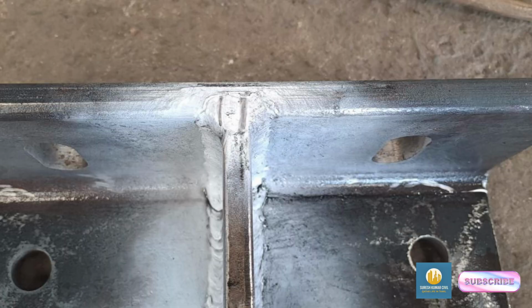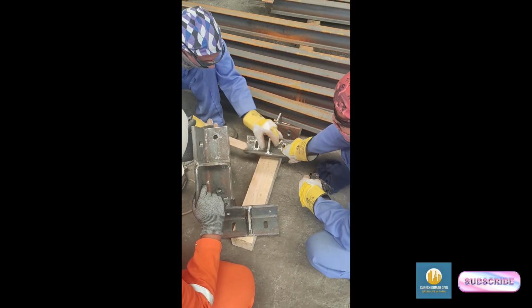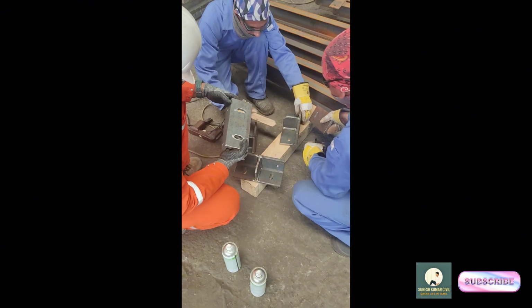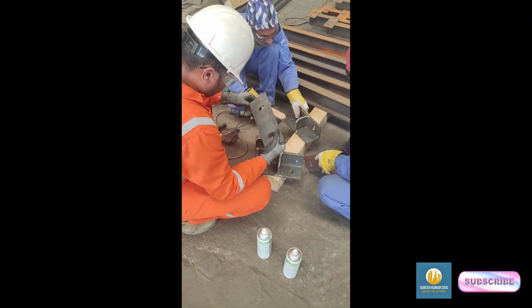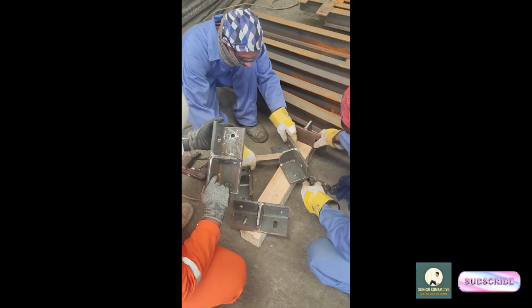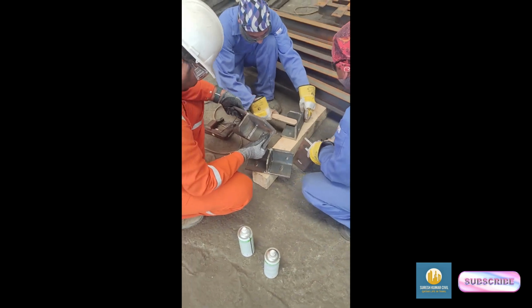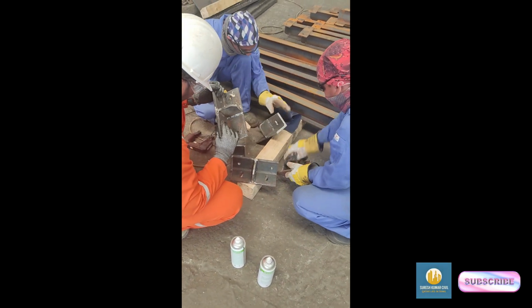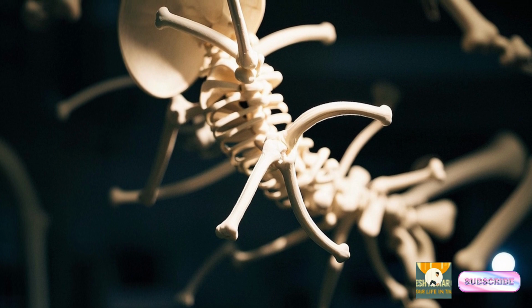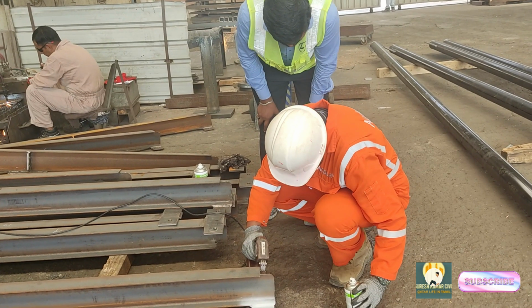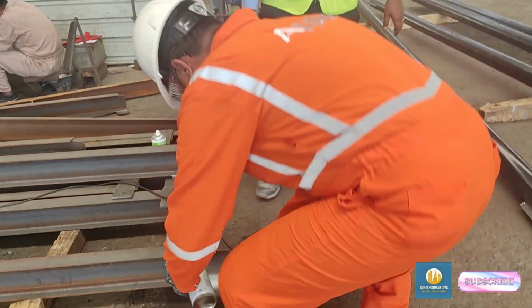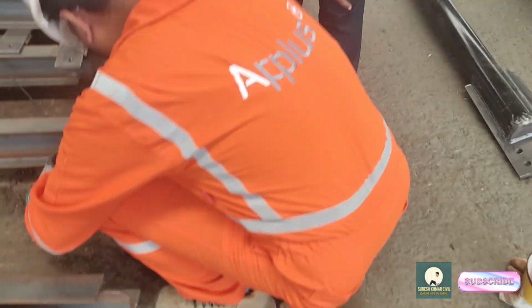Okay, so over here we can see that there is one defect on the joint. We have sprayed this solution on the fillet portion of this joint. This defect is exactly at the root of the joint. Actually, during welding, the weld metal penetration was more and the base metal was not fused properly. If we had done the RT test, we would not have been able to identify this type of defect, because this defect is present at the root of the joint where the X-ray beam cannot reach. But with the help of magnetic particle inspection, we are able to identify this type of surface breaking defect.